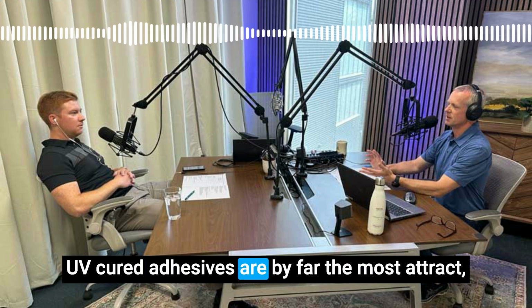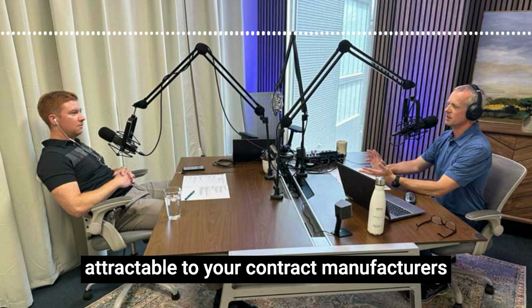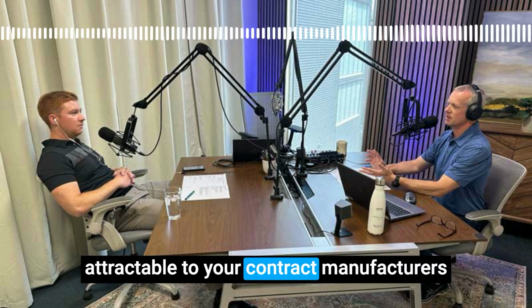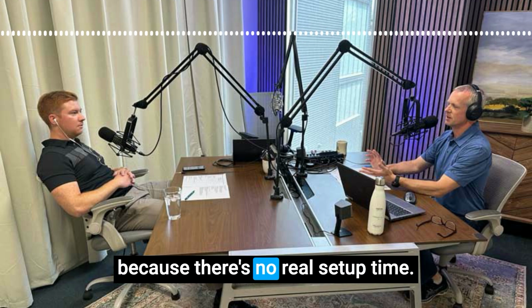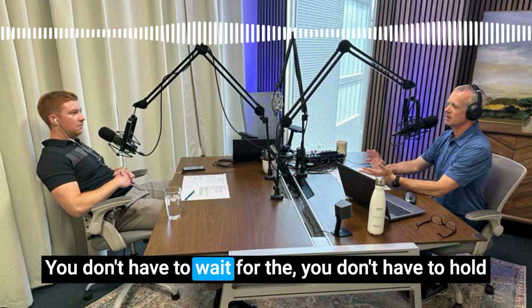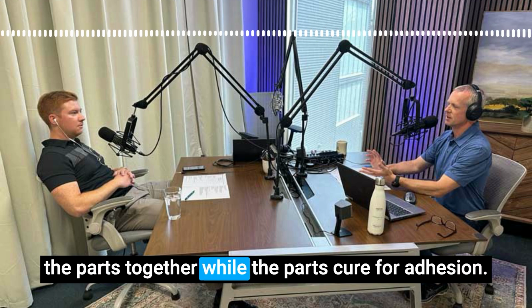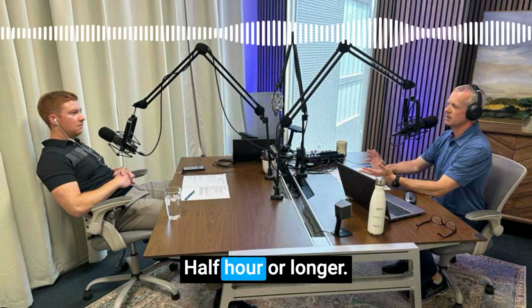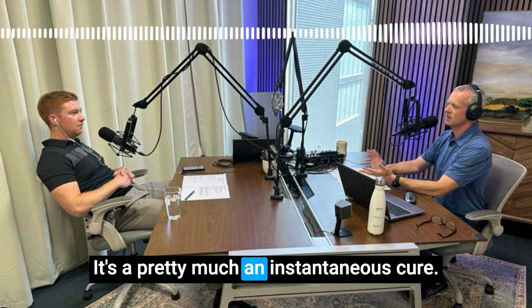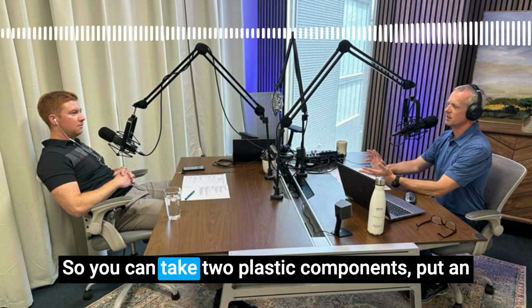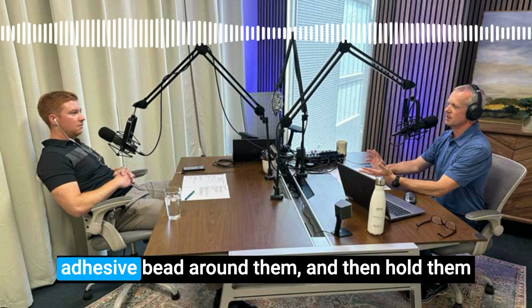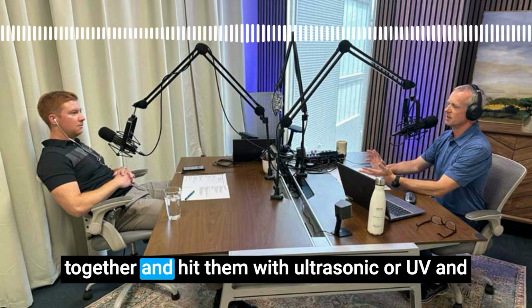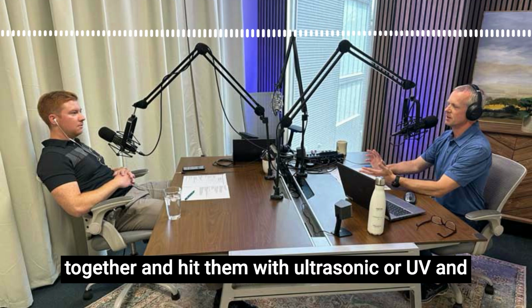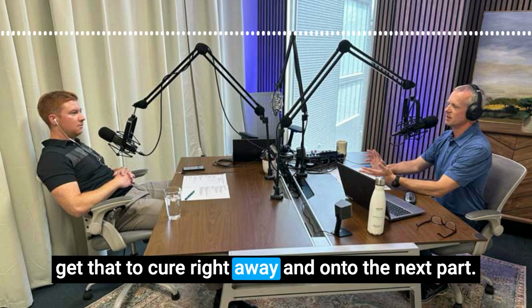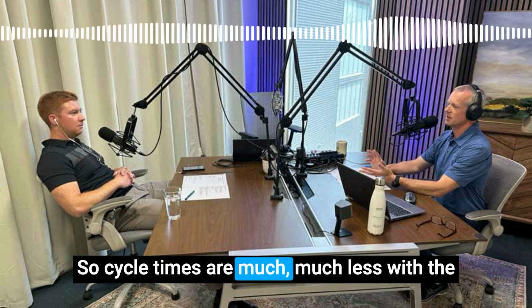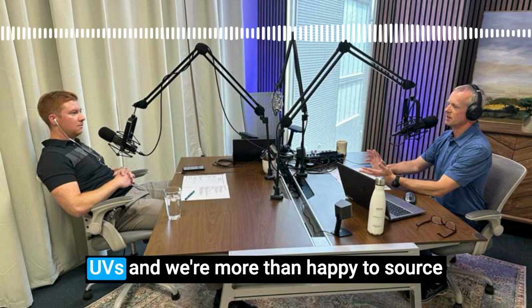UV cured adhesives are by far the most attractive to your contract manufacturers because there's no real setup time. You don't have to hold the parts together while they cure for half an hour or longer. It's pretty much an instantaneous cure. So you can take two plastic components, put an adhesive bead around them, hold them together, and hit them with ultrasonic or UV and get that to cure right away and on to the next part. So cycle times are much, much less with the UVs.